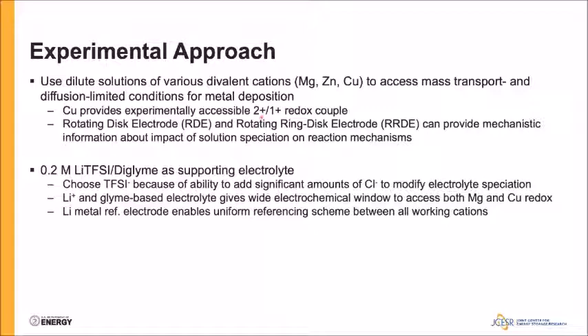TFSI we choose specifically because even though magnesium chloride and chlorides in general are fairly poorly soluble in these ether electrolytes, in the presence of TFSI, you can actually have significant amounts of chloride to modify electrolyte speciation. The electrolyte itself gives us a wide electrochemical window. Magnesium and copper are very far apart in terms of redox potentials. And the other benefit of using a lithium-based electrolyte is we can use a lithium metal reference electrode to get a uniform referencing scheme between all of our different working cations.